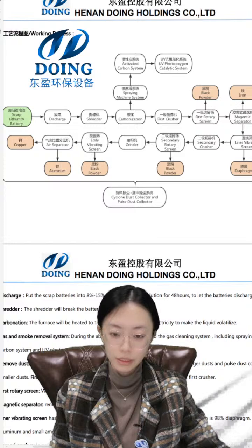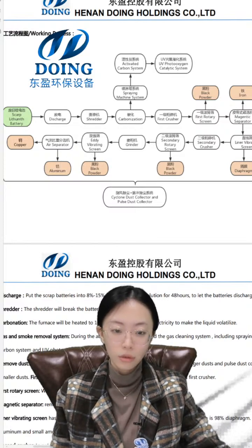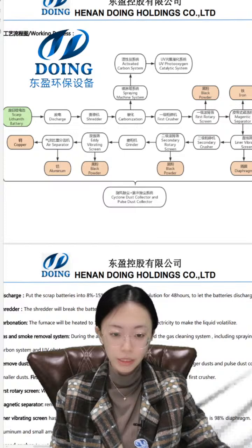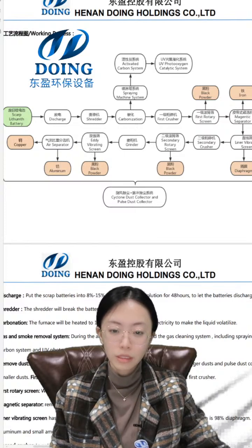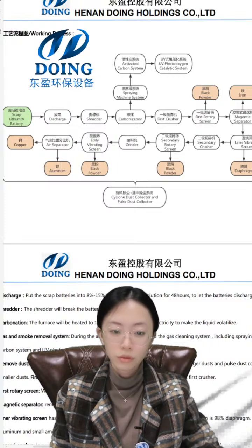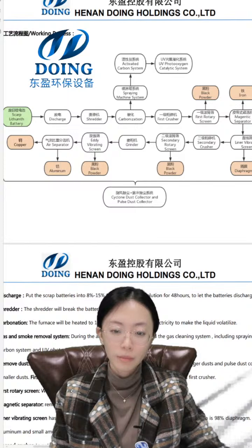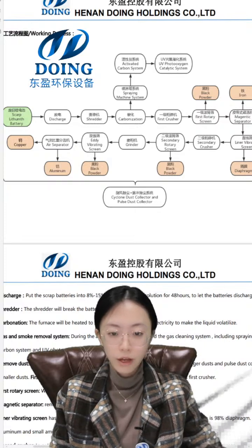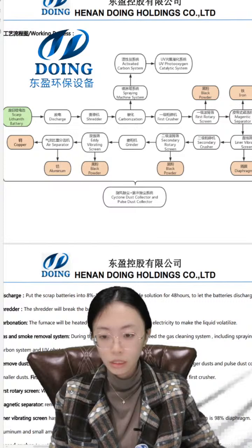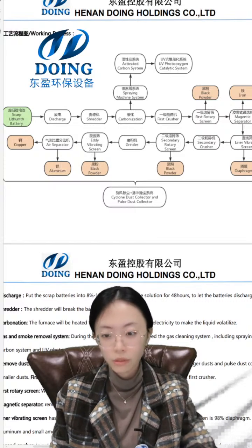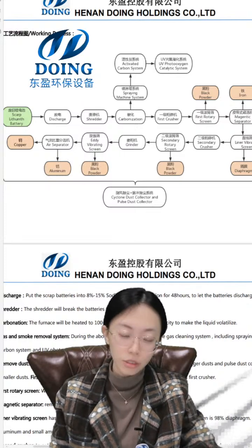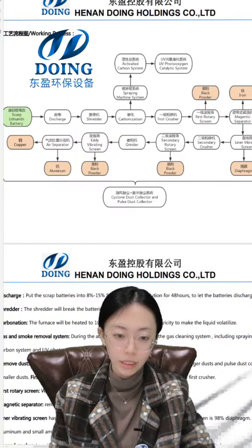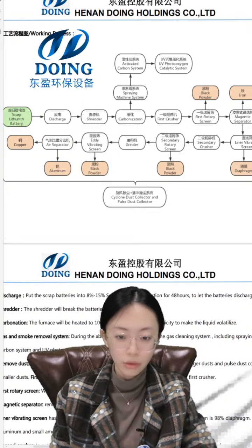Then is the carbonization furnace. We use electrostatic heating or gas heating. The temperature in the furnace is 100 to 450 degrees. So the electrolyte in the battery will completely volatilize to facilitate the subsequent harmless treatment. For a smaller capacity, like smaller than 500 kilograms each hour, or 100 or 200 per hour, it's not necessary to have the carbonization furnace. But if you have a large capacity, more than 1 ton or 2 tons each hour, we suggest you have this to dry your materials more quickly.